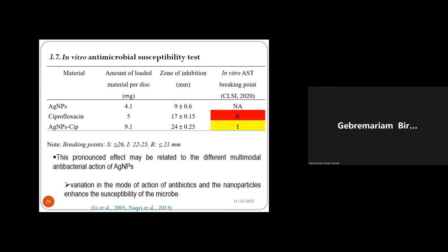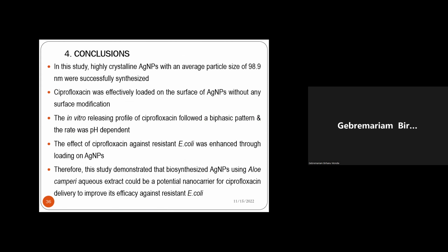But the loading of ciprofloxacin to silver nanoparticles obviously improves the efficacy of ciprofloxacin against resistant Escherichia coli. So when we come to the conclusion, in this study, highly crystalline silver nanoparticles with an average particle size of 98.9 plus or minus 3 nanometers were successfully synthesized. Ciprofloxacin was effectively loaded on the surface of silver nanoparticles without any surface modification.